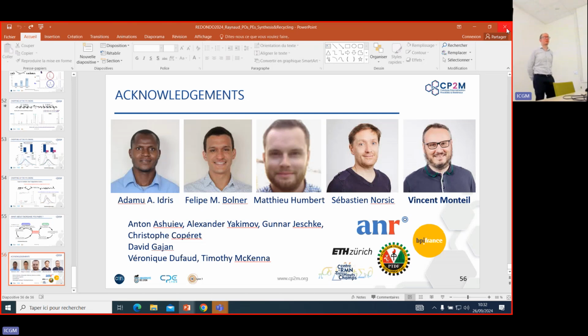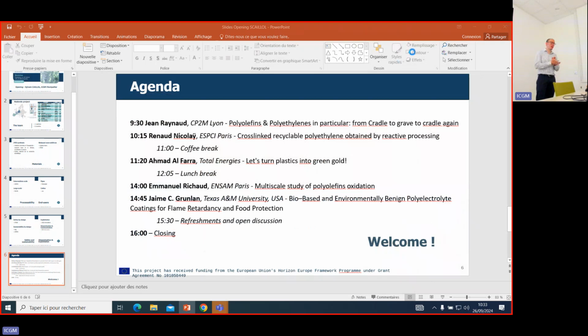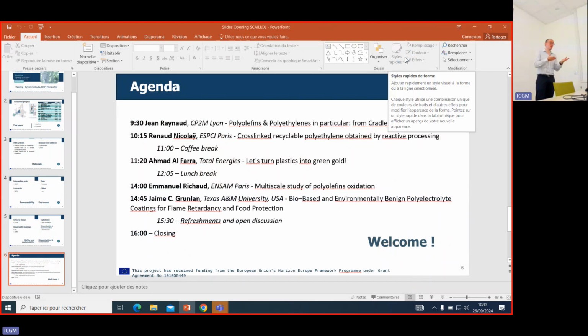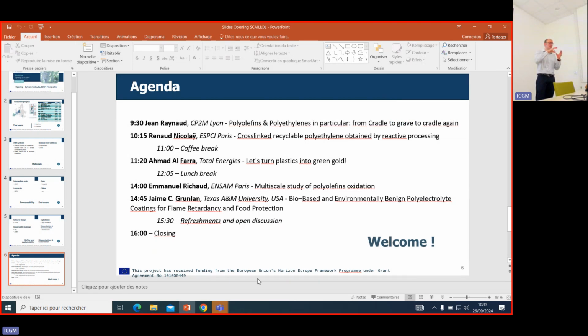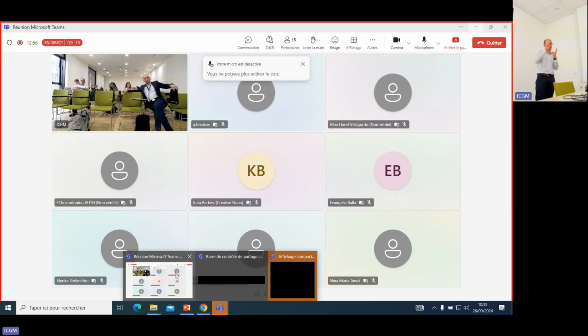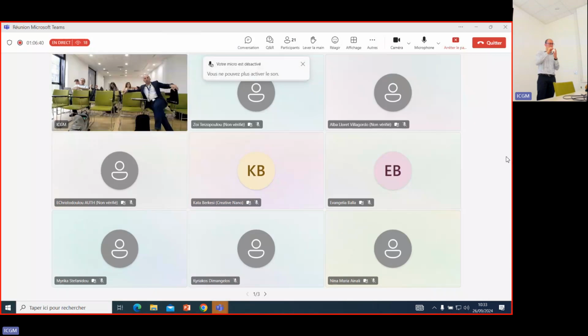Yes, basically. All the ligands that I mentioned are mostly inorganic ligands for the supported magnesium dichloride based catalyst system. You do have some Lewis base, and we tune by adding some Lewis acid to remove some of these Lewis base. The problem is this does not end up at the end of the polyethylene chain. The only thing that ends up is the first alkyl that comes from the aluminum alkyls.